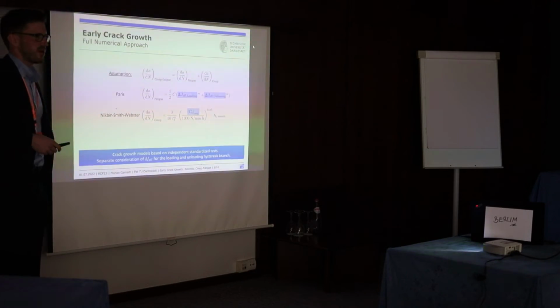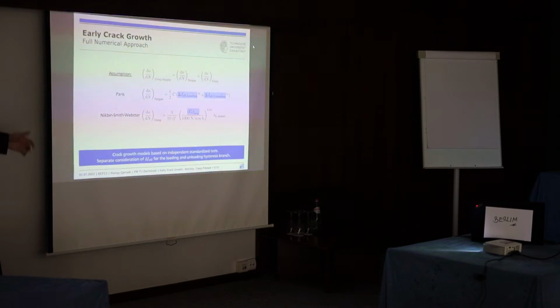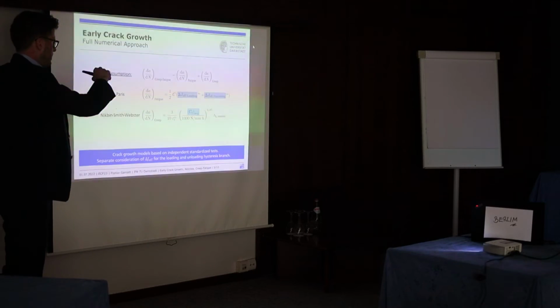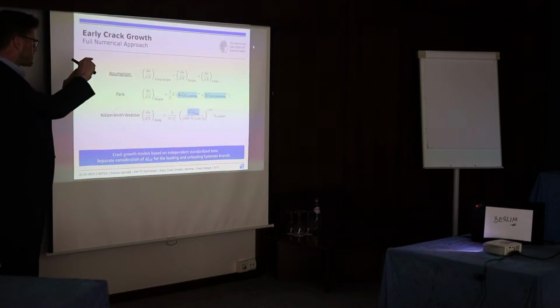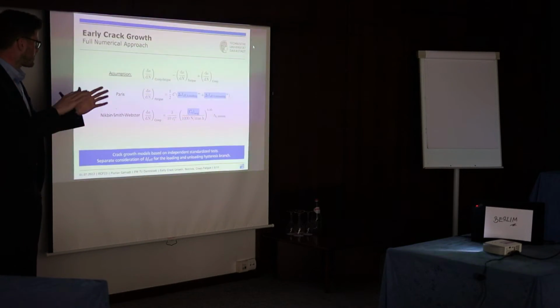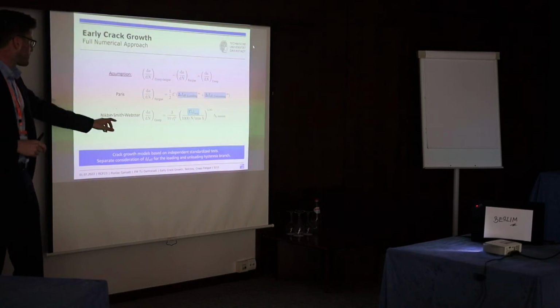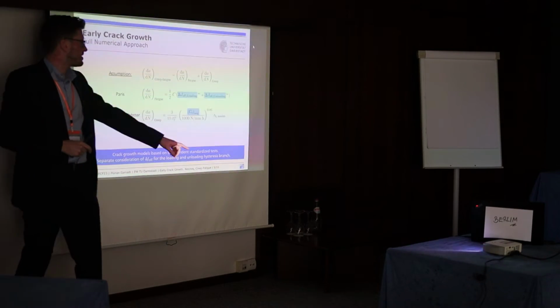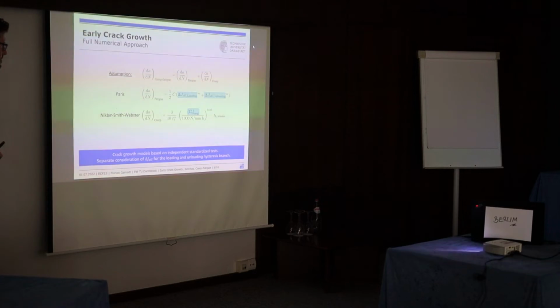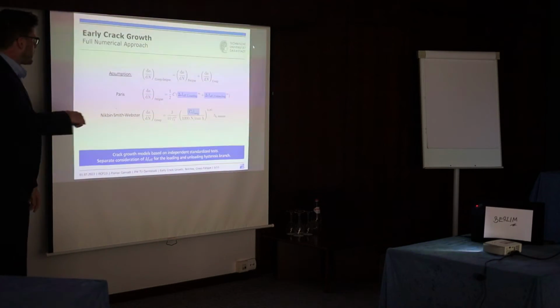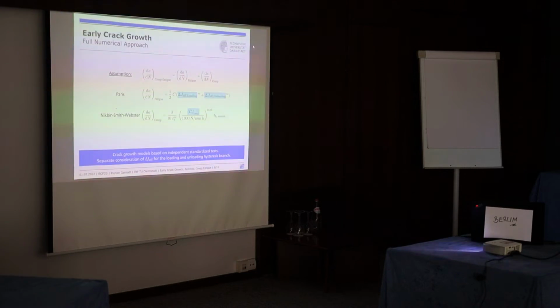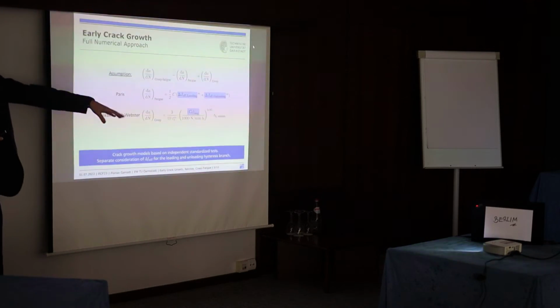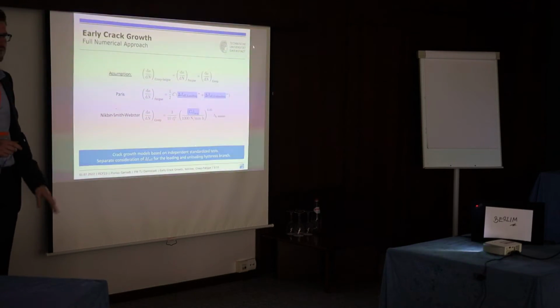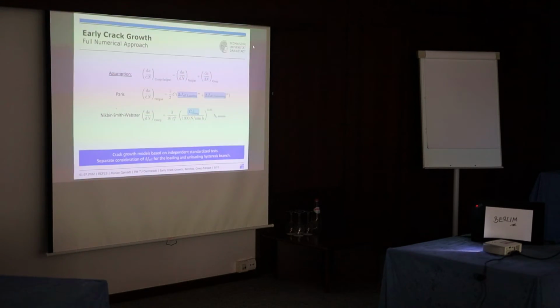For the fatigue crack growth part, we use Paris law, but here maybe the difference is that we use the crack tip loading delta J effective for the loading part and for the unloading part, so we differentiate here. And we use a Nikbin-Smith-Webster model based on a C_t average parameter introduced by Saxena to compute the creep crack growth rate. And the sum of both fatigue and creep gives us our creep fatigue crack growth rate. And the parameters of these models are determined by independent standardized tests.